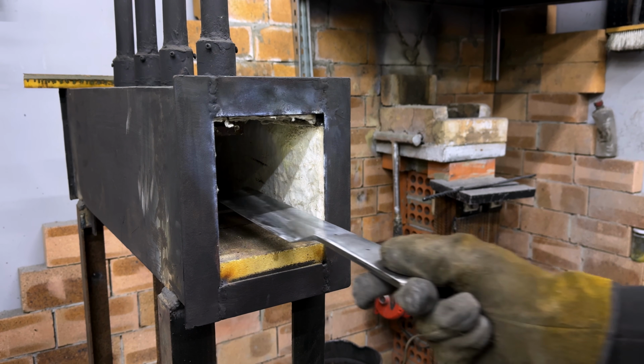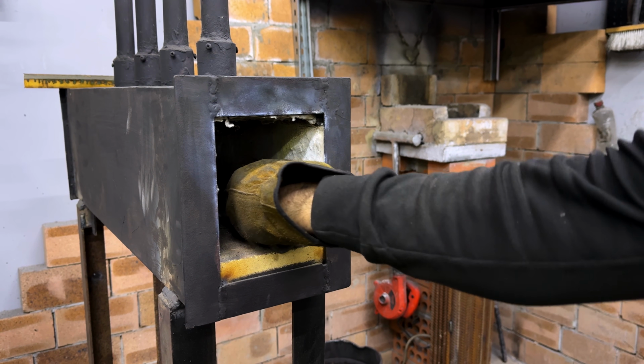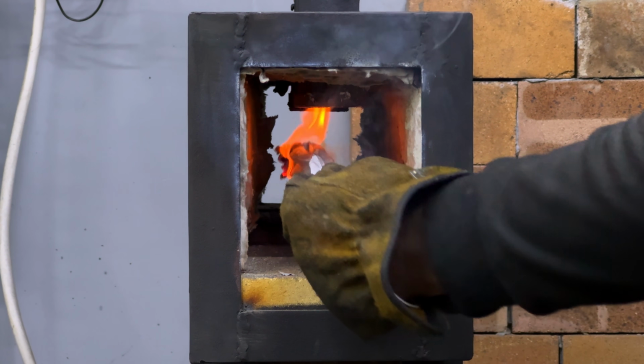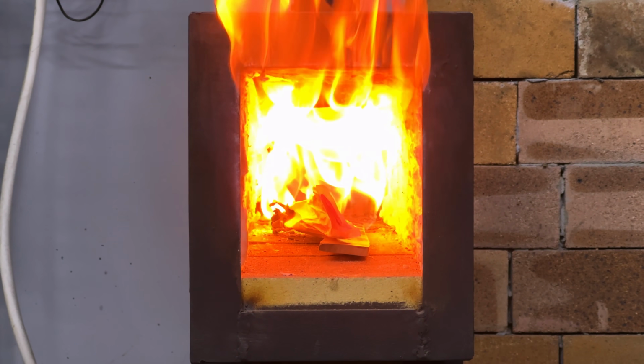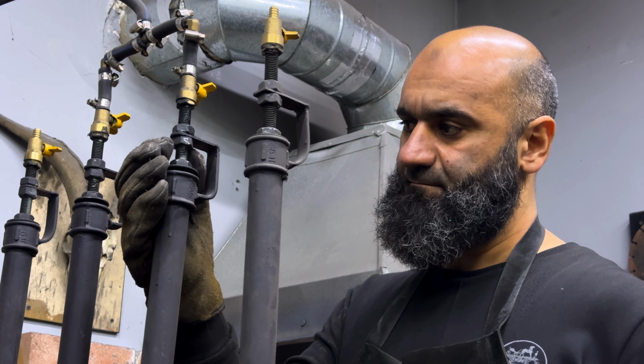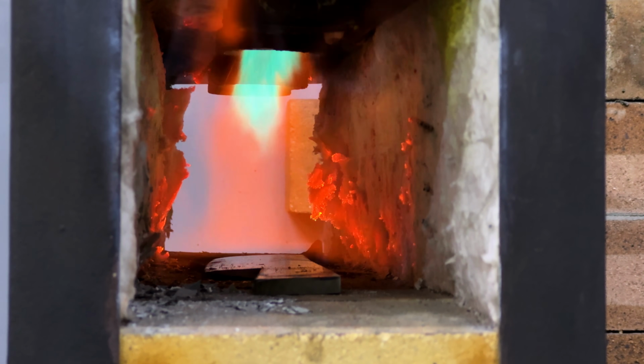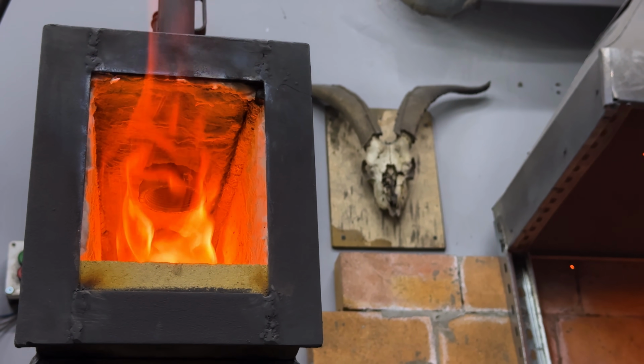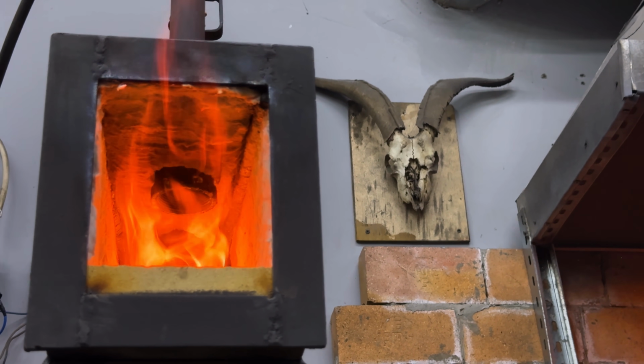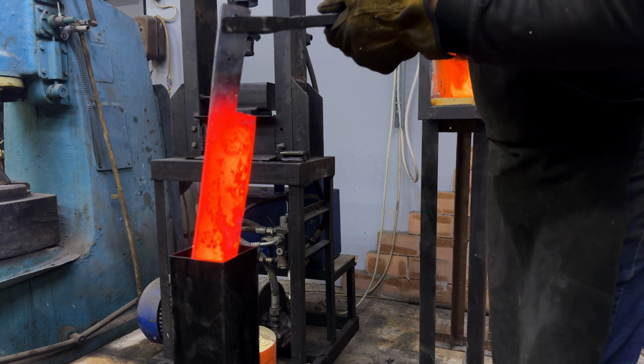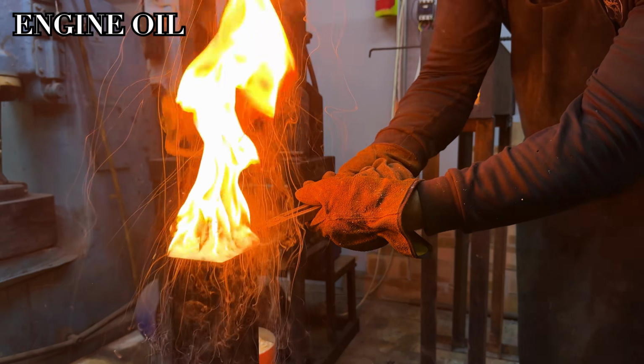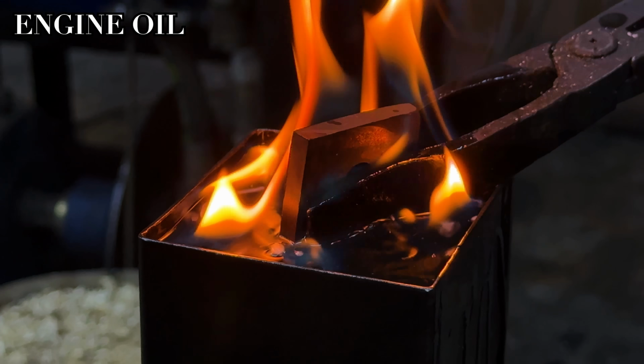Hardening time. This is a gas or electric furnace, more controlled than the coal forge. We're heating to critical temperature, around 800–830 degrees Celsius for medium carbon steel. Quench in warm engine oil, around 50 degrees Celsius. Warm oil speeds up the vapor jacket collapse for more consistent hardening.